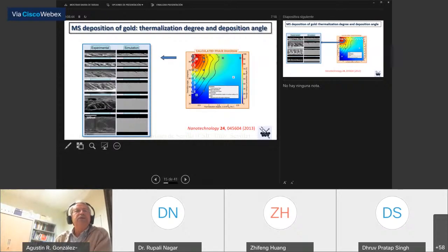Just to show you here the result regarding the effect of the deposition angle. Even if we have similar thermalization degrees here, we can move from this situation to this situation where we have a completely tilted nanostructure. Well, this is the experimental and this is the simulation by Monte Carlo simulation. And you can see here that indeed moving through this area is very critical. So increasing the tilting angle is very critical to get the nanocolumns.